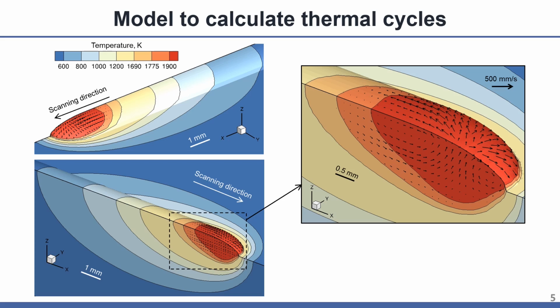The thermal cycles were computed using a well-tested three-dimensional transient heat transfer and fluid flow model. Here we show the three-dimensional temperature and velocity field during the deposition of grade 91 steel using directed energy deposition. Near the front of the molten pool, isotherms are compressed. However, due to high scanning speed, isotherms are elongated near the trailing edge.